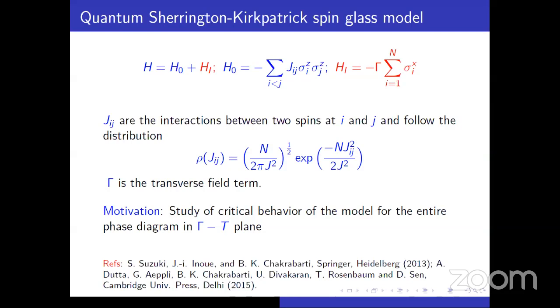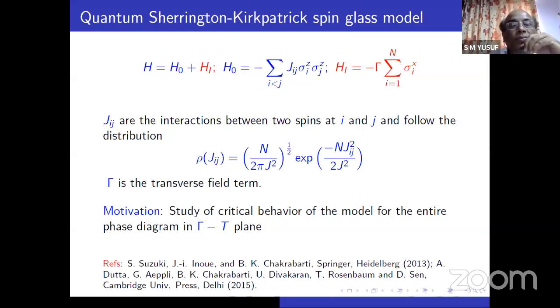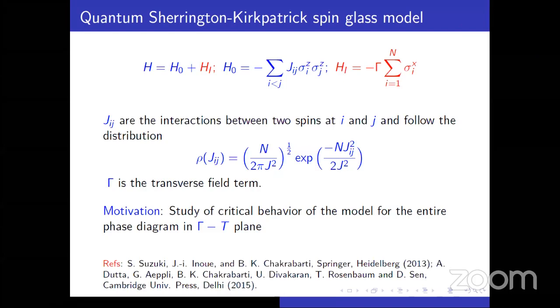So this is the Hamiltonian. H0 is, of course, the classical spin glass SK model, the Sherrington-Kirkpatrick model, the original H0. These are only the z components of the Pauli spin, sigma i z and sigma j z, with interaction among them, Jij, which is random, plus or minus, given by a Gaussian probability distribution, rho Jij.